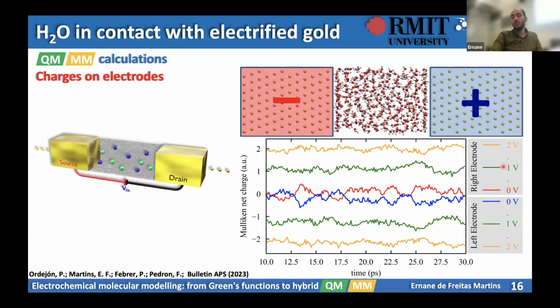With the right electrode above and the left electrode below, for the different voltages we apply, the surface gets charged. For example, the yellow curve here: the charge fluctuates around -2 in this case. This is the sum of all the gold atoms. Here -2, and here +2. In the case without a voltage, blue and red, the charge on each side fluctuates as expected because of the random distribution of water close to the interface. So this shows that this method could be applied efficiently to corrosion inhibition.